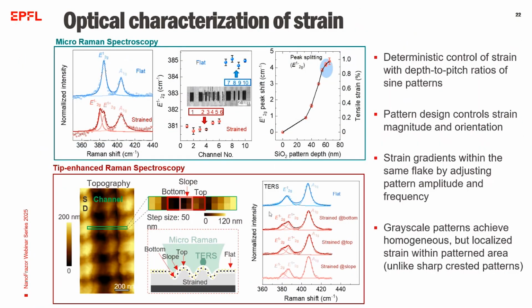To characterize strain, optical techniques like Raman spectroscopy are performed, and as intuitively expected, a higher aspect ratio of grayscale nanopattern results in higher tensile strain in the transferred material. And using Raman spectroscopy, we demonstrated up to 1% tensile strain in MoS2. And on the other hand, with tip-enhanced Raman spectroscopy, we analyze the strain distribution at the bottom, top, and the slope of this sinusoidal nanopattern. And as a result, we observe that grayscale surfaces provide more homogeneous strain distribution in the pattern region, unlike sharply patterned structures like pillars or rough crested substrates.